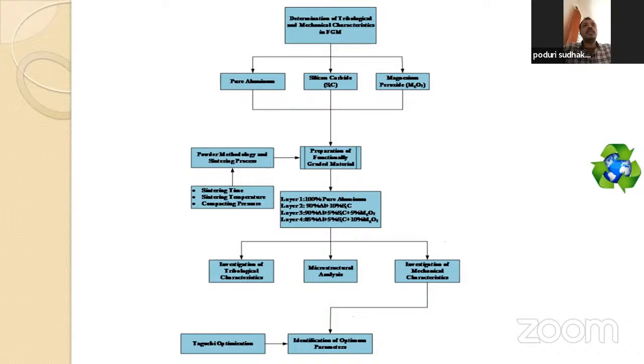They are impinged on the products, and thereby we have the sintering time, sintering temperature, and the compaction pressure. These are the process parameters we have taken. Basically our process depends mainly on the sintering time, the sintering temperature and the compaction pressure. But in the sintering process, it mainly depends upon the sintering temperature and the sintering time. Actually, the sintering temperature should be 70 to 80 percent of the melting temperature of the metal. Suppose you take the melting temperature of aluminum, it is 673 degrees centigrade. Then 70 to 80 percent means we can keep our sintering temperature from 400 to 600 degrees centigrade, and the sintering time is also very important.